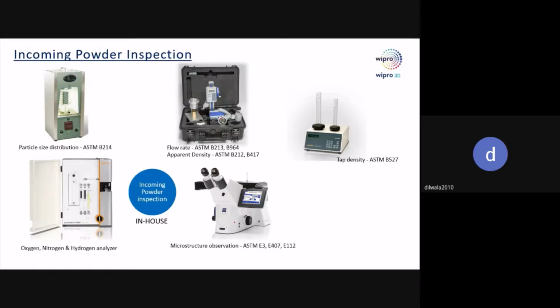Then we do ONH analysis. We check in the powder what the ONH levels are. It is required to monitor the ONH levels because these define the mechanical properties. Then microstructure analysis. We do microstructure analysis for the coupons which have been printed from the specimens.